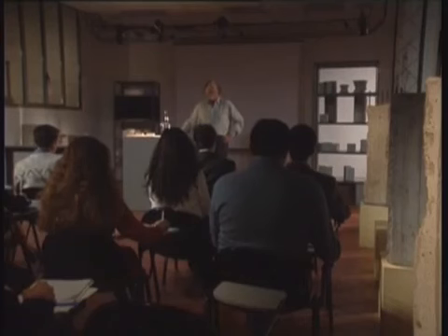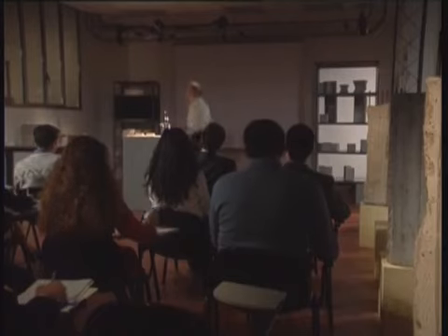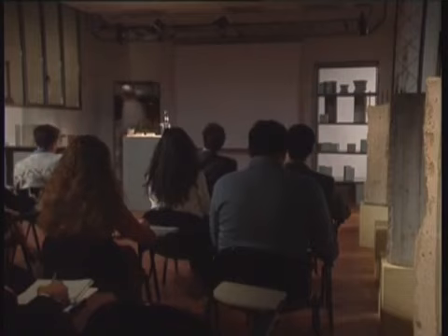Using as little water as possible in the cement paste is the main rule. And the more aggressive the environment in which the construction is built, the lower the water-cement ratio to be used. When this rule is not observed, deterioration of the concrete structure is inevitable with the passing of time. The latest statistics show that the most widespread cases of deterioration are due to the chemical effects of carbon dioxide in the air.